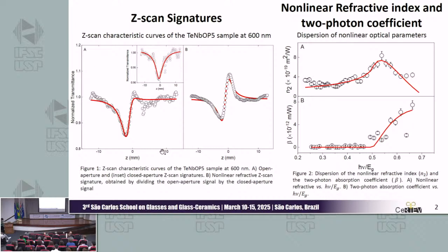As we can see, the samples exhibit a high nonlinear refractive index of about 10 times greater than silica in the infrared. In the visible range, around 600 nanometers, it's increased threefold. The dispersion is related to two-photon absorption through the Kramers-Kronig relation. In this curve, the red curves represent the theoretical fitting based on the Sheik-Bahae model for amorphous semiconductors, showing excellent agreement with experimental data. So that's all. Thank you for your attention.